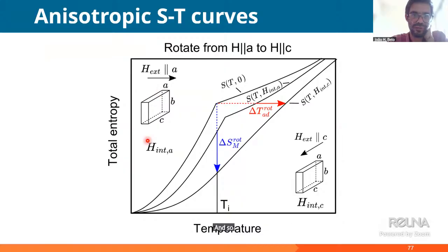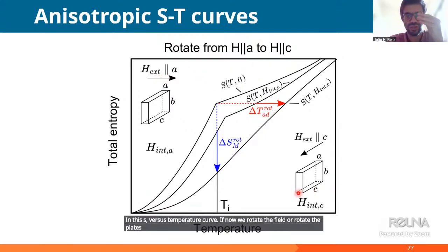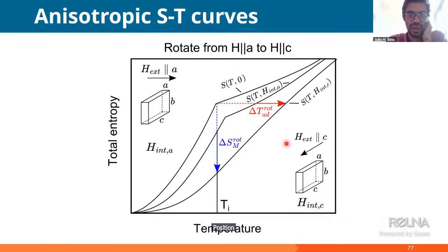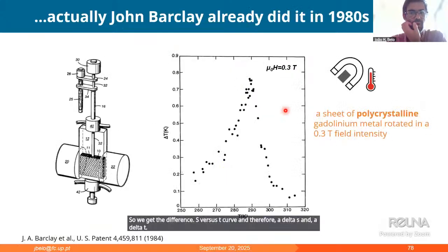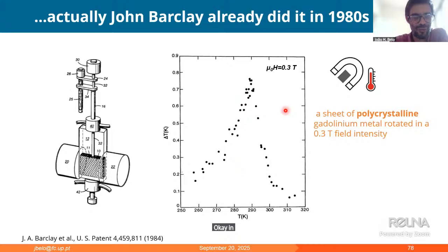So by rotating, again taking the example of the plate, the field is applied perpendicular to the plate, and we are lying here in this S versus temperature curve. If now we rotate the field or rotate the plate, either way, we just have to change their relative orientation, we indeed change the internal field, so we get a different S versus T curve, and therefore a delta S and a delta T. Okay, in fact, we found out later, this was already partially discovered by John Barclay in his patent from '84